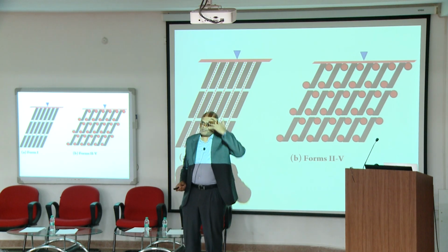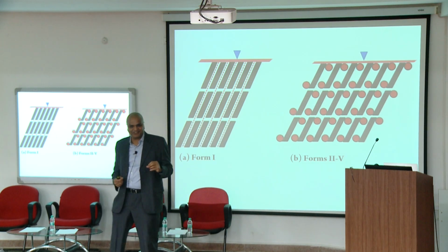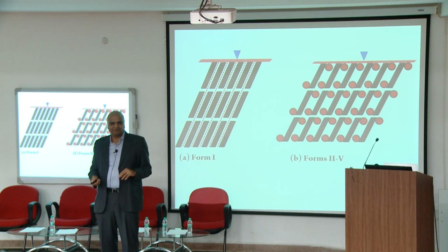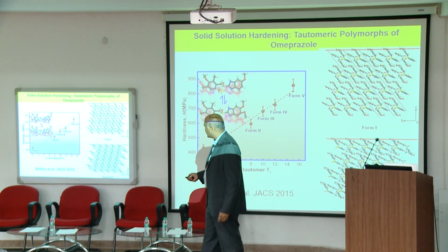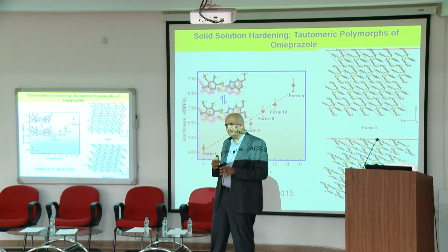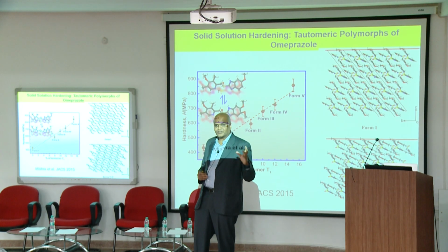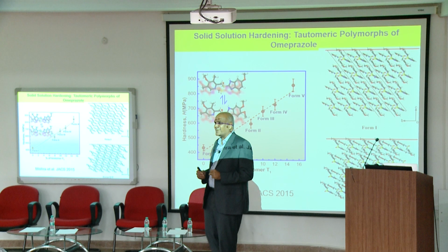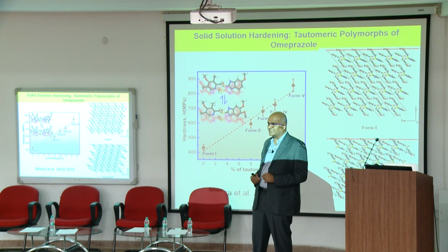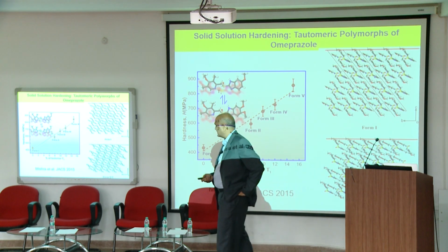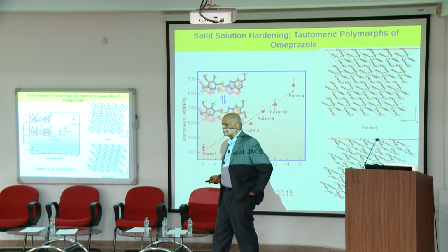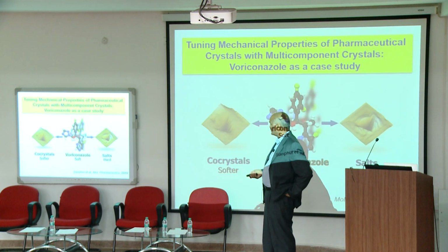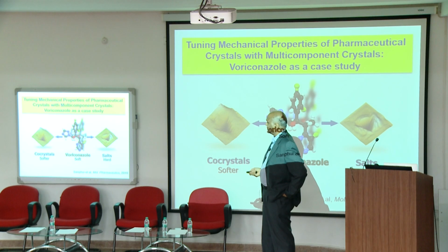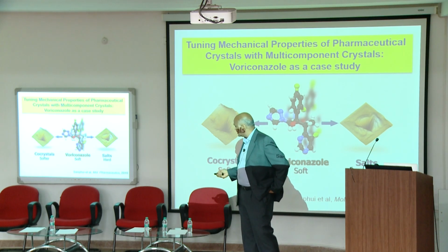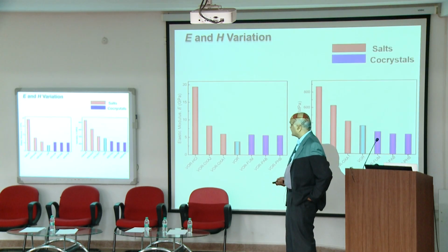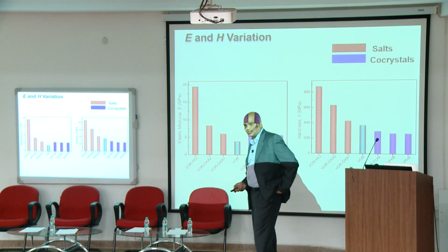So this paper, my metallurgy friends will like it. It's called solid solution hardening. So you play around with the tautomer content as a percentage, and you can actually change the hardness. So you can do these kinds of tricks, which metallurgists have known for centuries or maybe decades at least, and you can apply these to change the hardness of a molecular solid. So we learn these tricks can be applied to molecular solids as well. And in fact, you can think in terms of either forming co-crystals or salts. This is on voriconazole, again another API, and so you can essentially play around with E and H variation.